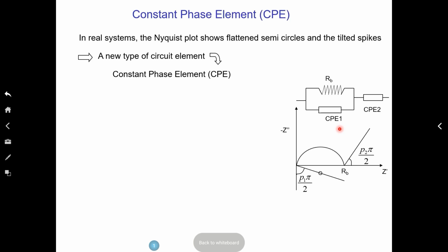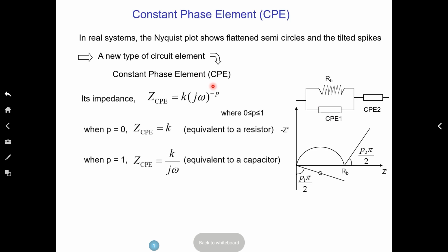So it was some hodgepodge picture. So this constant phase element will further distort meaning. You see it in this case, I'm drawing something that looks like a semicircle, but the center of the semicircle is not lying on the real axis. It's actually lying on an axis that makes an angle. So your semicircle gets depressed.